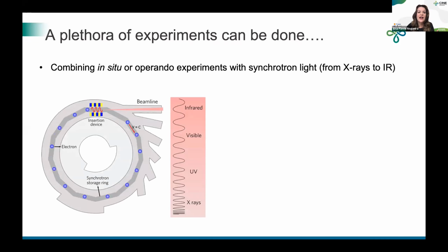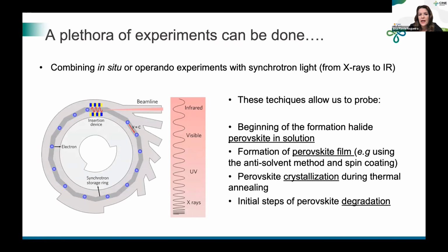So in order to understand more about these perovskites, we can combine, for instance, in situ and operando experiments, not only with synchrotron light, but also with very common light sources that you can find in our lab. But talking about the synchrotron light, it can go from X-rays even to infrared. Applying these techniques to perovskite materials, we can track the formation of this perovskite in solution. We can track the formation of this perovskite film, and even see what's going on during, for instance, the crystallization step. This is really important for the perovskites. And also we can follow the initial steps of the degradation. I'm going to show you only 2 examples here because of the time.